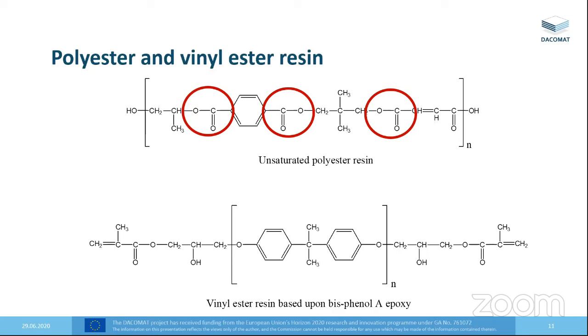So I've just shown on the unsaturated polyester these ester linkages, which is where the name comes from. These are very vulnerable to attack by water. If you look at the vinyl ester, you don't see these apart from at the terminal parts of the chain. So this is the kind of backbone of the chain. And then we have to cross-link that to make a thermoset resin, which is a rigid resin. You can't melt it and form it after it's gone through its curing process. And generally for that, we will use cross-links, which are either made of styrene or methacrylic acid, or a mixture of styrene and methacrylic acid.